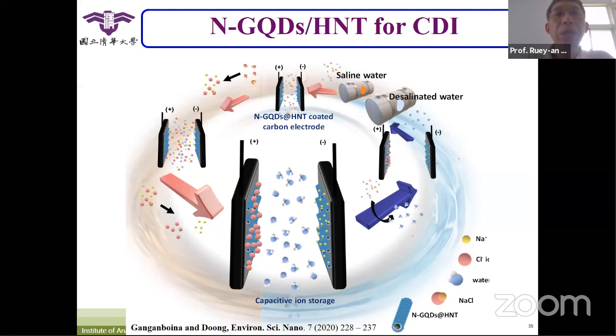Here we just use the graphene quantum dots with halloysite nanotube. Hope that you remember that we use this material for supercapacitors. Here we use the same material but just add one nitrogen dopant, to use for capacitive deionization. We just apply some brown waters or gray waters to get inside. They contain some contaminants and ions. When they pass through the cells, all the ions will be removed. They absorb on the surface here, and only water molecules can penetrate. After the treatment, the color changes from pink, for the contaminants that contain some impurity, to blue, the color of pure water molecules, so that we can get the desalinated water here.